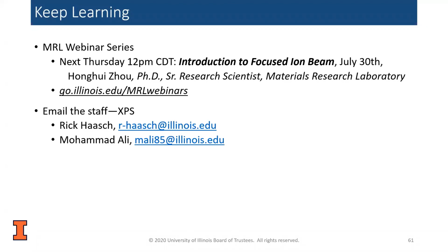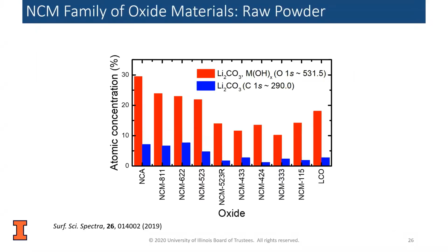Now going to the two questions here, Rick. One question is for slides number 26 and 27, where you give some materials composition as measured by XPS. Did you actually do surface sputter cleaning for such measurements? If yes, how sure are you about the percentage of oxygen, since the sputtered oxygen actually goes back to the surface due to the high reactivity? No, these are not sputtered, because we didn't want to sputter these, as that would alter the chemistry, besides preferentially removing light atoms and everything else. Sputtering can be quite reactive, and it can actually cause reactions.